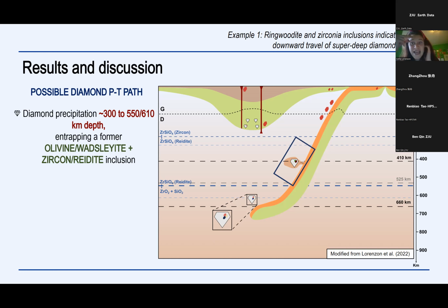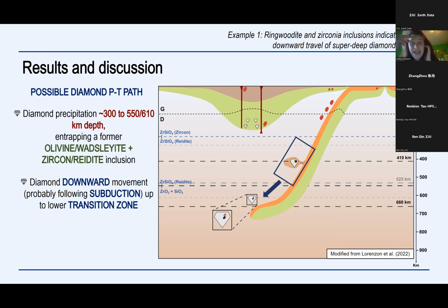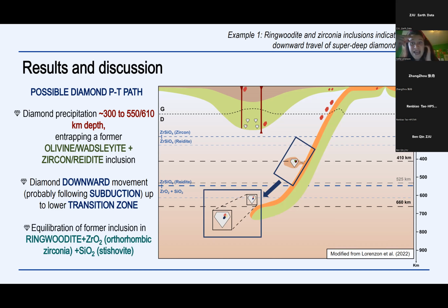zircon or reidite. Subsequently, this diamond traveled downward toward higher pressure, probably following the subduction, and reached the lower parts of the transition zone, where the former inclusion composed of olivine or wadsleyite plus zircon or reidite re-equilibrated into a new one composed of ringwoodite plus orthorhombic zirconia and stishovite.